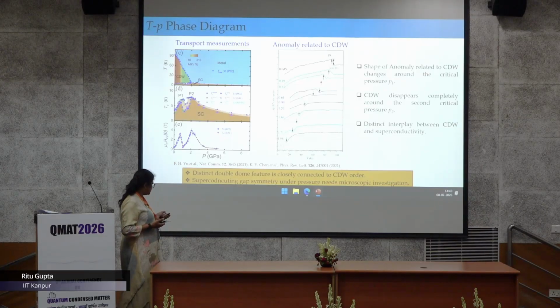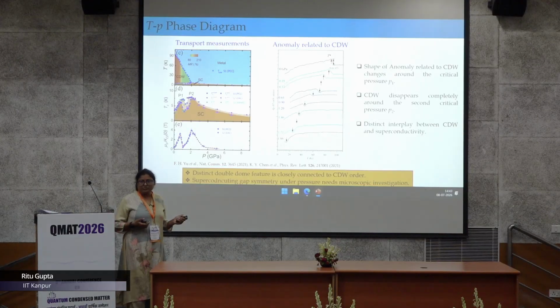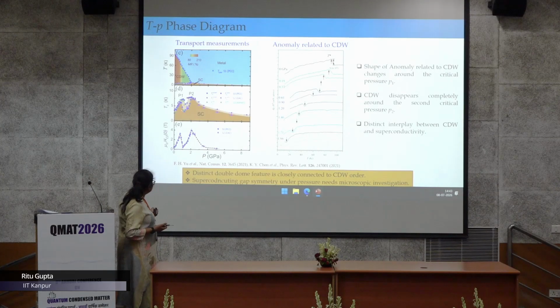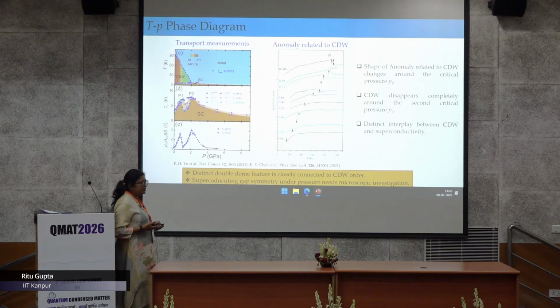That's why Tc increases. But what is happening around this first critical pressure P1? So you see a double dome like feature. What is happening around P1 was not very well understood, and the same feature you see also in the upper critical field, as a function of pressure.